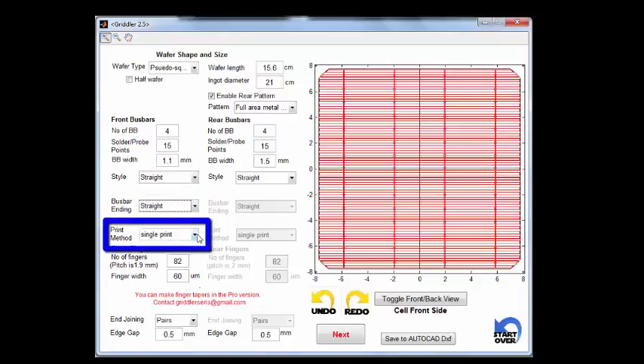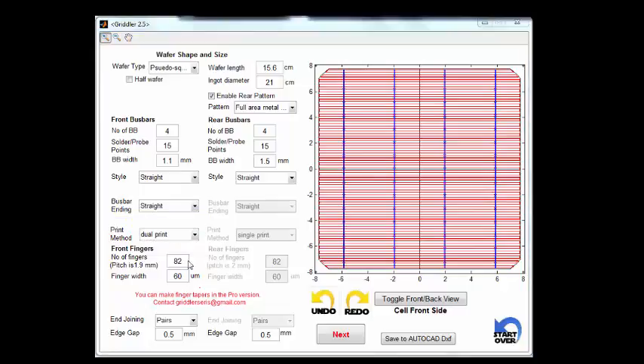Print method: single print means the bus bars are drawn in the red layer, that's the layer contacting the semiconductor. If we chose dual print, we get the bus bar sitting in the blue layer, which does not make contact to the semiconductor — it only makes contact to the red layer. So effectively that simulates a dual print process where the first print lays down the fingers that fire through to make contact to the emitter, and the second print lays down the non-aggressive bus bar silver paste which only touches the metal fingers.